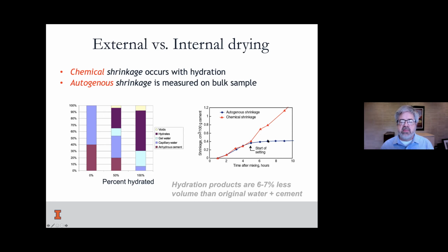And now with set, the autogenous shrinkage is going to start constraining and creating stress in the microstructure, because the free collapse of the material, because it's a fresh flowing material, can no longer occur. It's gone through set. So we have this deviation of chemical shrinkage and autogenous shrinkage. When that happens, boom, that is a time where stress begins. This is a time where that autogenous shrinkage starts creating an internal state of stress that causes cracking. And that's why we need to address this internal problem.